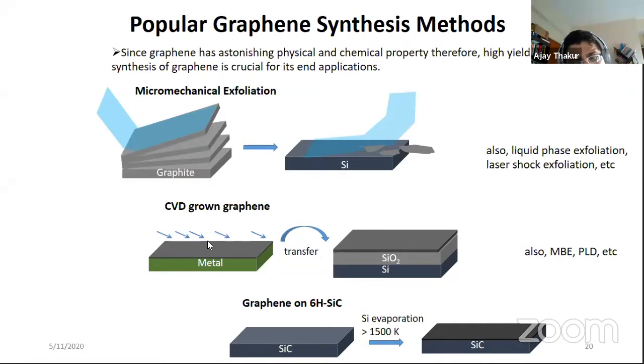The other technique is chemical vapor deposition grown graphene. In this, what is basically done is you take a metallic substrate, in this case copper. Then inside a chemical reactor, you send in a controlled amount of a hydrocarbon, and you decompose it so that the carbon from that deposits onto the metal substrate and forms a layer. By controlling the growth parameters, one can ensure that large areas of a monolayer of carbon are grown on top of the copper substrate. And that's how the first reports of CVD grown graphene came about.